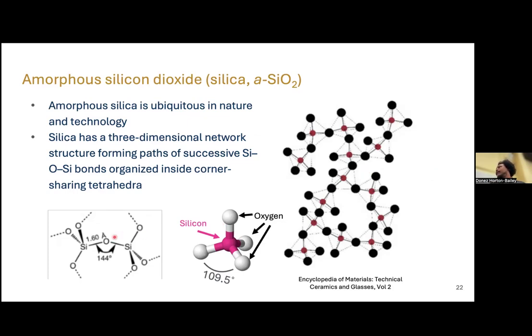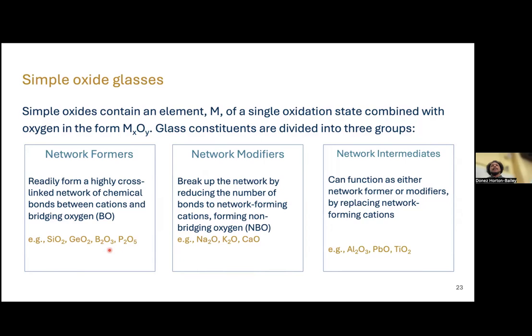Typically in a crystal, you have a very well-defined bond angle and bond length, but in an amorphous material, you have a little bit of a distribution of angles, and this is what allows us to have an amorphous structure as opposed to a very rigid crystal structure. Oxide glasses, I study simple oxide glasses where you just have a single metal or semiconductor and oxygen. There's a lot of research on more complex oxides where you have multiple metal ions, but in that case, you also have a lot of electronic effects that I'm not really interested in studying, and it just makes the project a lot harder.